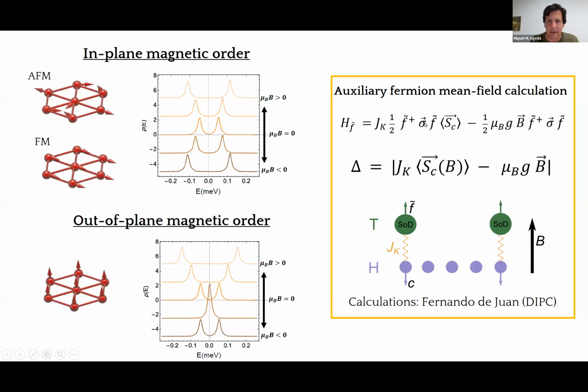Basically, he carried out this calculation in which he takes into account the interaction between the isolated magnetic moments and the conduction band electrons. So this is the Hamiltonian that he used, and he calculated the density of states of the system assuming different magnetic orders. So here's the expression for the separation between the peaks. It has two terms. One takes into account the strength of the coupling between the magnetic moments and the conduction electrons, and is proportional as well to the magnetization of the conduction electrons due to the magnetic field. And the second term is just proportional to the Zeeman splitting.